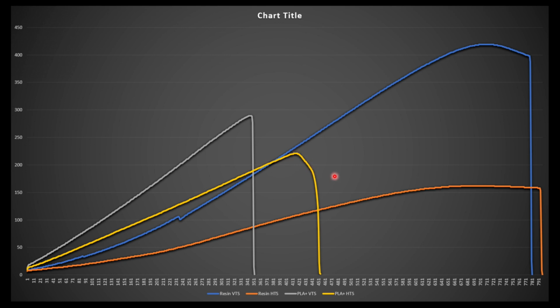Now, if we look at the resin prints, both of them actually failed pretty much the same way. Now, the horizontal sample is much less, so you can't see it as much, but because it's a much lower amount of force because it had a smaller cross section. But both parts kind of came up, they peaked, they yielded, and then they spontaneously broke at the end. So it's kind of a mixture between the vertical and horizontal PLA test samples. So they did have some yield to them, but they did not continue yielding. They ended up at the end breaking in a brittle way, kind of like a piece of glass would.